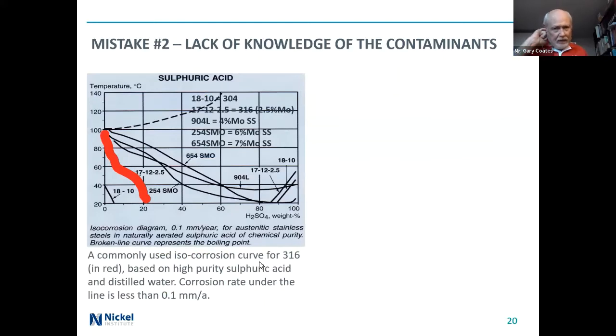So let's look at the isocorrosion curve for 316, for different stainless steels in sulfuric acid. The one in red here, I've painted in with PowerPoint, and I don't have a steady hand, so it's not quite the same as the original curve, but it's close. You can see that there's a limited range of usage of 316L in dilute sulfuric acid. You get up to 20%, and you can only use it at essentially 20 degrees C. As we get higher in temperature, the amount of acid it will tolerate is less. And this line represents a corrosion rate of 0.1 millimeter per year. Underneath the line is less than 0.1 millimeter per year.